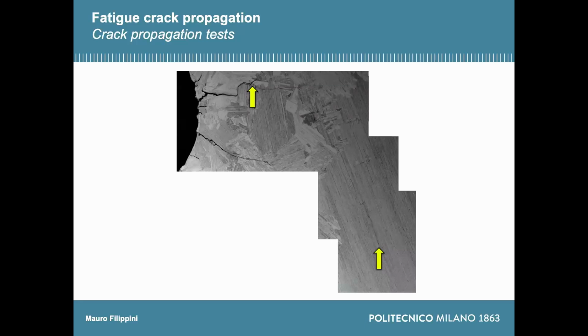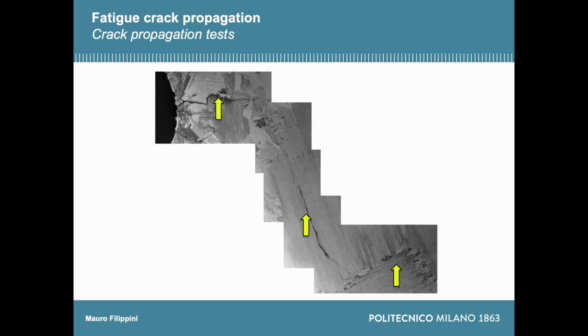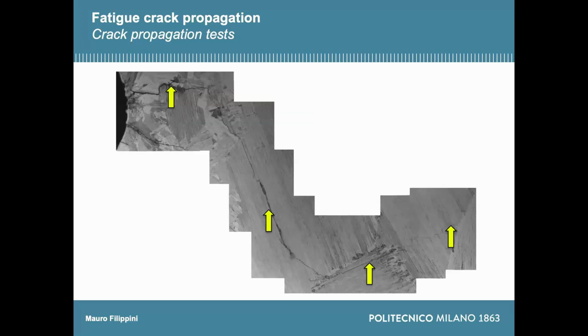So you can see that in spite of some principal crack, you have some other cracks that are already generated within this lamellar colony in this position. So you don't see it, but you have a long crack going around, and the tip is about here. And again, this is the evidence after a few cycles that the crack has propagated in this way. You just have to consider that this distance is in the order of a few hundred microns. And again, there is definite evidence of a big influence of the microstructure on the crack propagation.